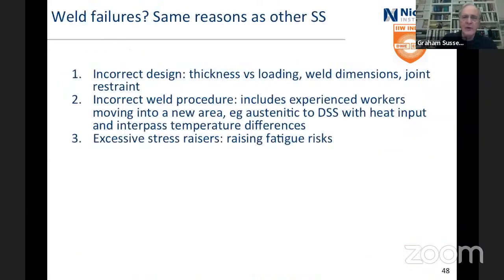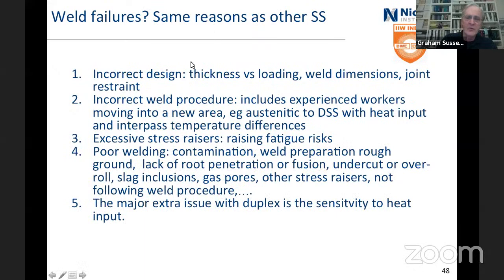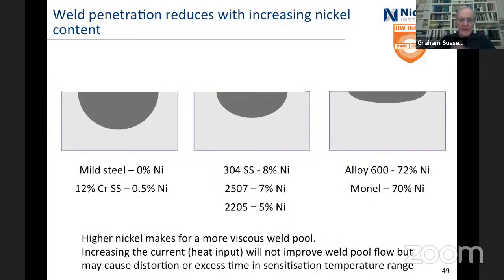So why would welds fail? This is basically the standard things that all stainless steels might fail from, and I'm not going to go through them in any detail. There was talk about it before. The major extra issue with duplex is the sensitivity to heat input and what that does to the phases. Here we're talking about this level of nickel, usually, and so it's not as great penetration as mild steel or as the low-level ferritics, and it's not as bad penetration as the high nickels. It's somewhere in the middle.